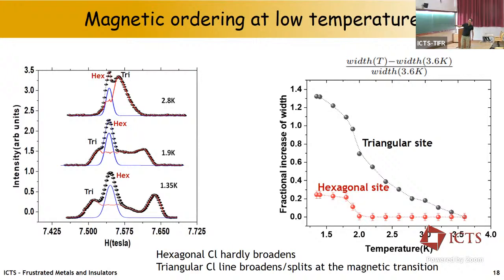And so across the transition, there are marked changes. Actually, the hexagonal site does not change too much. Here, that's the increase of the width of this site. There is something, but it's an increase by 20% of the line. But the triangular site is changing a lot, with drastic broadening, and also it looks like we now have different sites in the ground state, in the magnetic state. So this is the evolution of the line width of the triangular site. So how do we understand that?